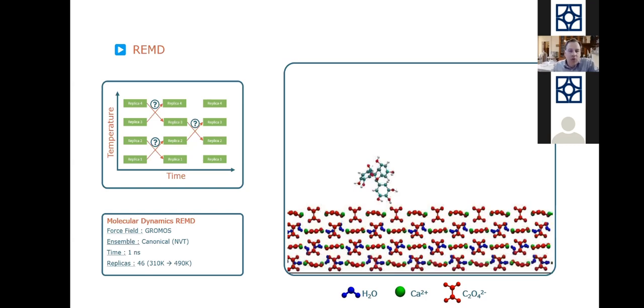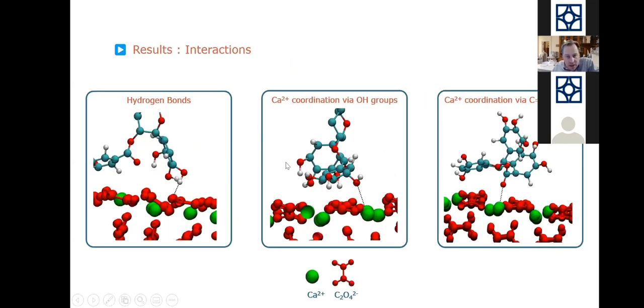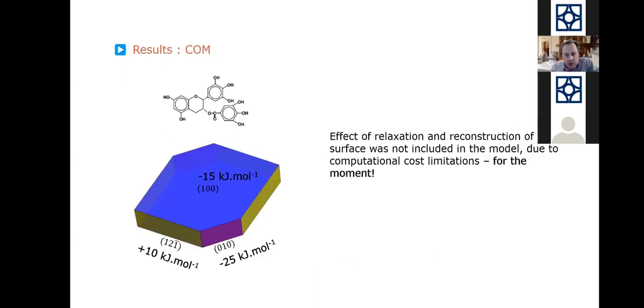Okay, then, this is our way to find the adsorption geometry of the catechine molecule on the surface. And so we can extract our geometries, and then analyze with DFT the adsorption of these molecules at the surface. This explains the mechanism of adsorption, and maybe also allows us to propose a mechanism of this corrosion, if you remember. So the complexation of a calcium ion, these green balls here, with the molecule. So the final aim of the study would be to propose a mechanism of this corrosion process. And this is what we wanted to do.